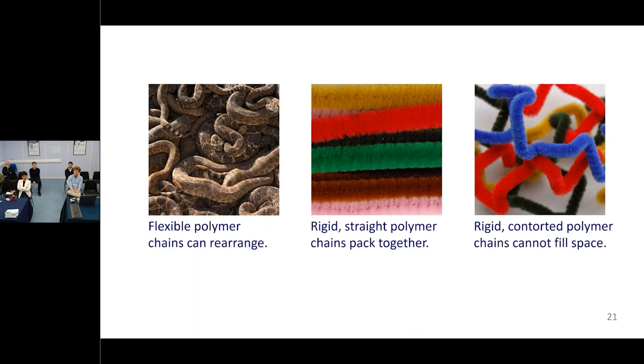You can design polymers as a chemist which are very rigid, which can't change very much, but they tend to pack very effectively. You often end up with something you can't process, can't do very much with at all. Our trick is to try to make a polymer where you reduce the conformational flexibility. We have usually no, or highly restricted, rotational flexibility in the backbone.